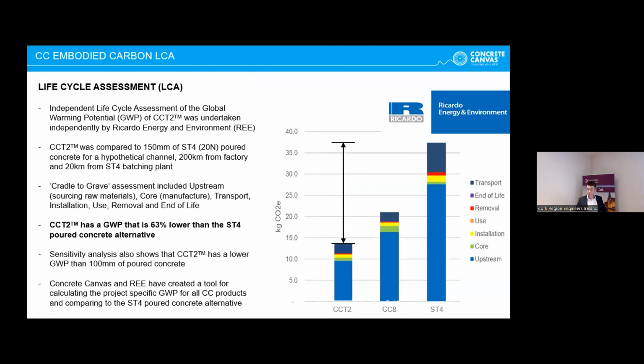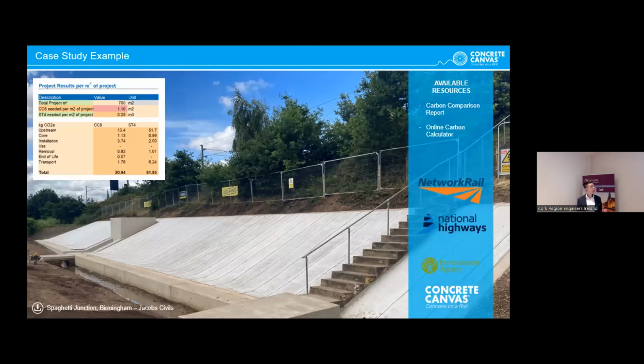Part of the report was also an interactive carbon tool. You'll see on this slide on the top left-hand side, the carbon tool allows designers or clients to input all the data for a particular scheme or for a particular project, and it can compare a GCCM product with an incumbent poured concrete or hard armor lining solution, and it can actually factor in what the exact carbon savings is on a particular scheme. A key thing to this is obviously location of the project. You can see on this particular scheme from Birmingham and Spaghetti Junction, which was a Network Rail and National Highways scheme headed up by the Environment Agency, they replaced the incumbent solution, which was 150 millimeters of poured concrete, with a type 2 GCCM specification. On this particular scheme, there's a 66% reduction in the global warming potential. So that's just an example of where the tool can be used. And we all encourage that it is used on schemes in the UK and Ireland.